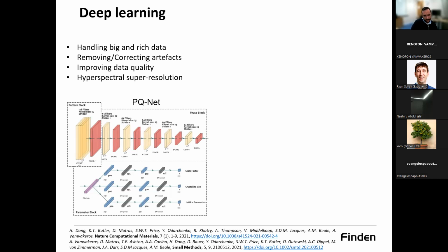So one of these developments was PQNet, the parameter quantification network. That was a supervised learning approach. And in that case, we generated hundreds of thousands of diffraction patterns very quickly, in a couple of tens of minutes, to train the network. The training also lasted 10 to 20 minutes, so a very fast process.